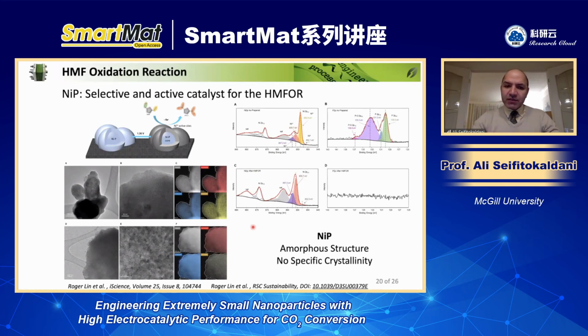So we started working with the nickel phosphorus. We synthesized that, but then we leached it out, basically reduced the NiP to just nickel on the surface. And we obtained this core-shell structure. At the surface, you have the nickel. In the core, you still have nickel and phosphorus. And we show that through different XPS analysis or even just EDX and SEM analysis to see how this amorphous structure is generated. We got, in fact, very interesting results, very high selectivity, very high current density.